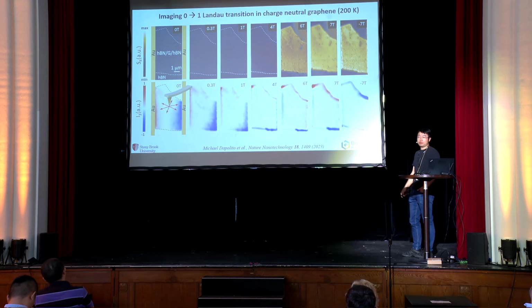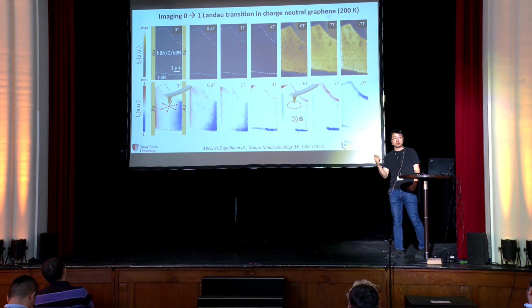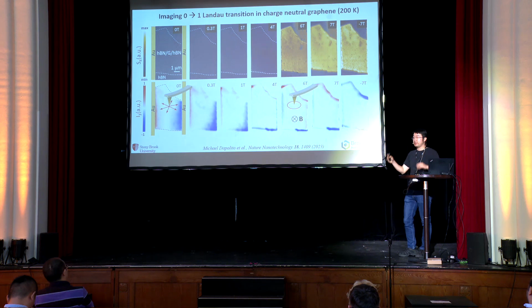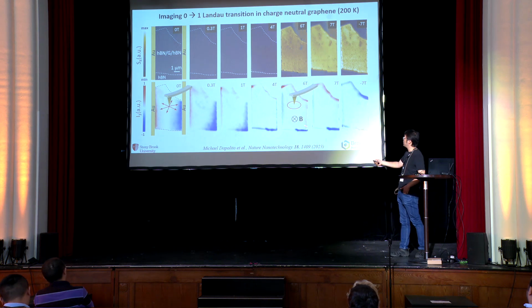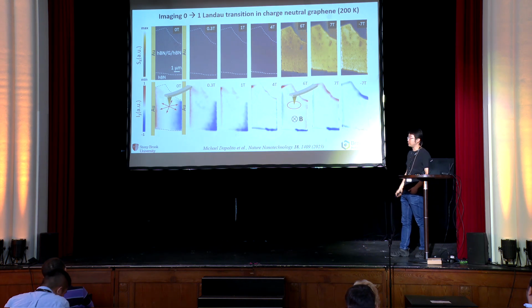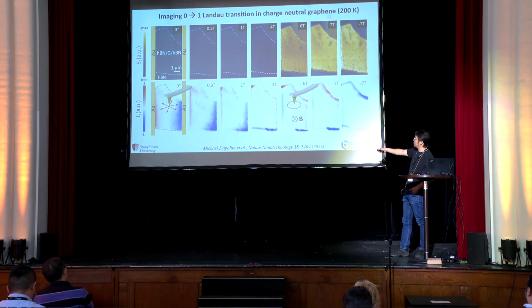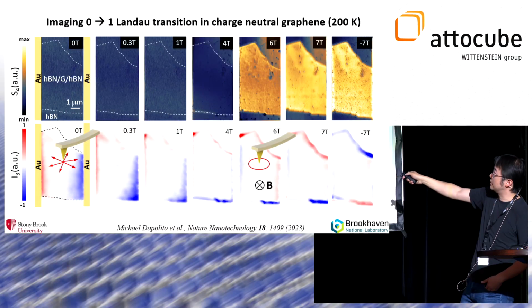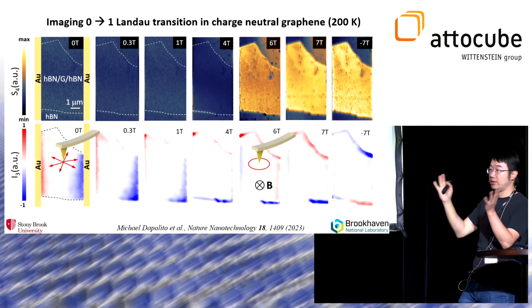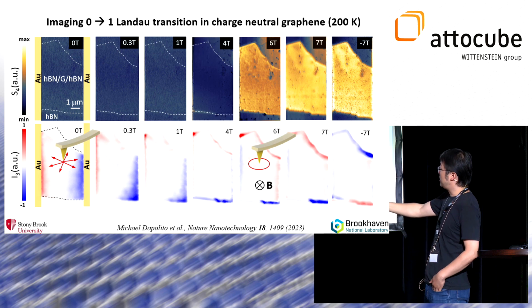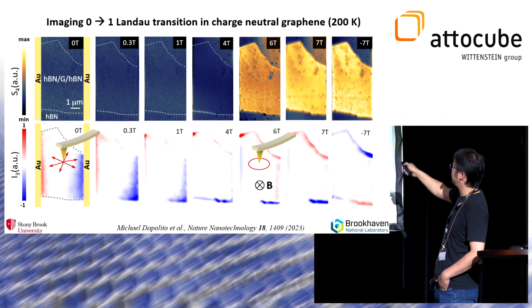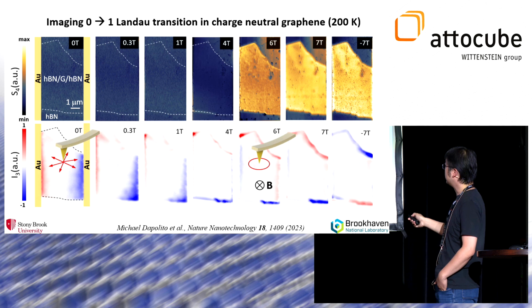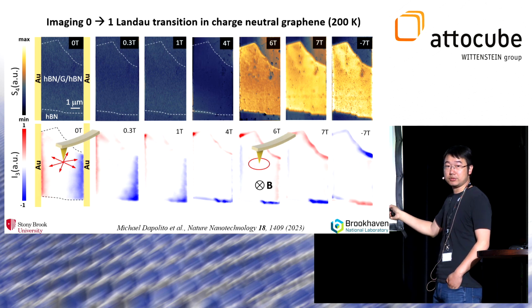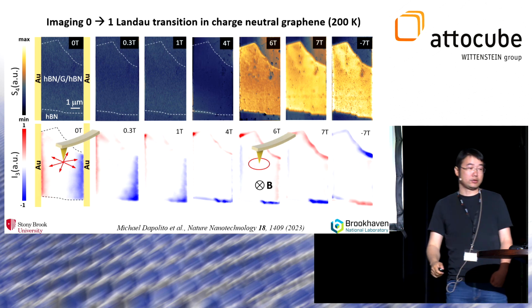And in high magnetic field, you will induce photocurrent, but this photocurrent will rotate due to the Lorentz force. You will rotate around the tip, right? Very naive, simple picture, so that you can now access this edge mode that is unidirectional. On the top edge, your current is to the left. On the bottom edge, your current is to the right, or the other way around. It doesn't matter which direction. Of course, if you switch the magnetic field, you will see this direction switches as well. There are some defects here that you can also see. There are some p-n junctions here.